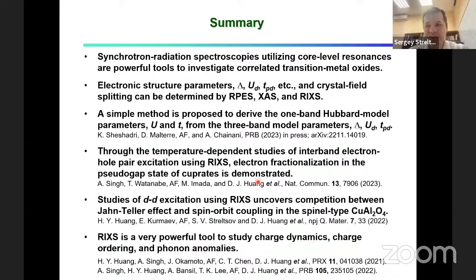Atsushi, it was very interesting, and of course, over the years we really became familiar with RIXS, which is an extremely useful and powerful technique. This copper aluminum O4 was more or less a problem which came from me, and we were really interested in which state, Jahn-Teller or spin orbit active one, is characteristic for this cuprate in particular, and RIXS was actually the only technique which could distinguish between these two states. Thank you for your insightful input. And collaboration was very